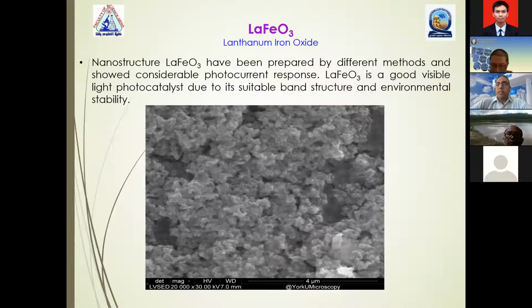About the generation of perovskite, it shows very high photoactivity. For example, we tried lanthanum iron oxide, or lanthanum ferrate, prepared by different methods, which showed a considerable photocurrent response, in nanostructured materials as well. This material is a good visible light photocatalyst due to its suitable band structure and environmental stability as well.